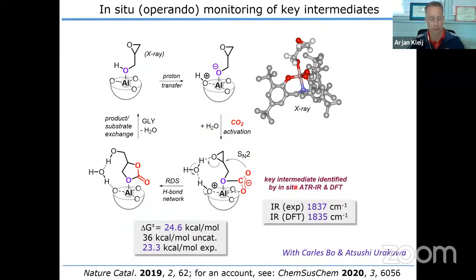Well, we looked at that in much more detail. So we collaborated with two colleagues, Carles Bo and Atsushi Urakawa, to not only look at this theoretically from a computational point of view, but also from the point of view of in situ analysis. So that would be operando in situ infrared or ATR IR analysis. And we know that the reaction in the presence of our aluminum complex starts with the coordination of the alcohol. So that was a little bit of a surprise, but later on we found by X-ray analysis that we could actually support this view.